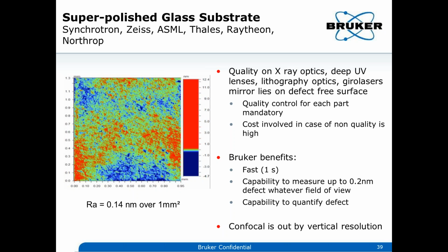So you can get a very large field of view. Here, for example, you can see the field of view is about 1 by 1 millimeter, which is fairly large. On the resolution, you see the RMS is 0.1 nanometer, right? We measure this with the PSI technique. If you use techniques like confocal, then you have to choose a very high magnification objective to get this kind of Z resolution, but then you sacrifice the field of view, right? So you're only able to measure a very small field of view, which is limiting again because you want to analyze a very large area very quickly. And so with our technique, you can measure a very large area very quickly with very high resolution.